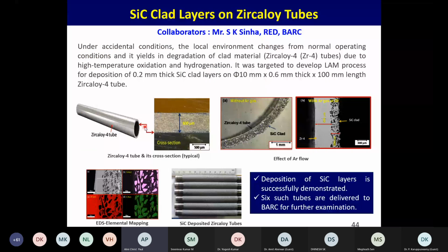Another fundamental and very nice study we did is the deposition of a silicon carbide layer on a thin zircaloy tube. The tube thickness is 0.6 millimeter, and you have to deposit a 0.2 millimeter silicon carbide layer. We tried and successfully did it, and this work is very important because we are developing it to take care of post-Fukushima challenges in reactor technology, specifically high temperature oxidation and hydrogenation. So these are the things we are trying and building.